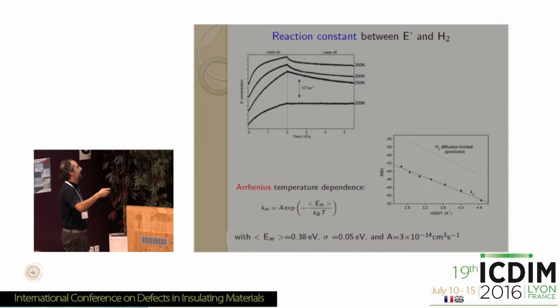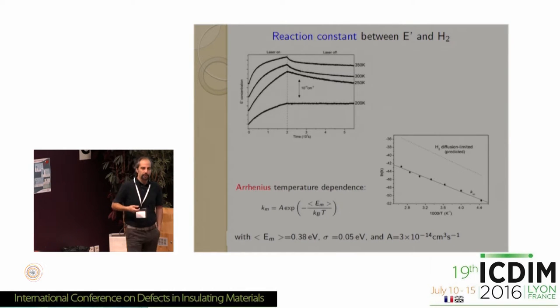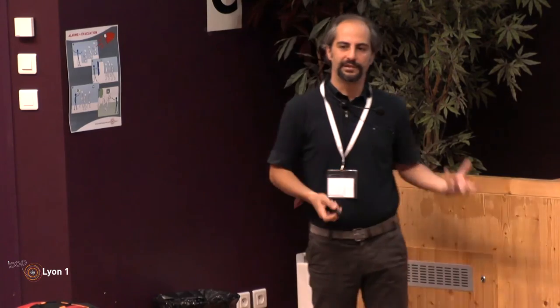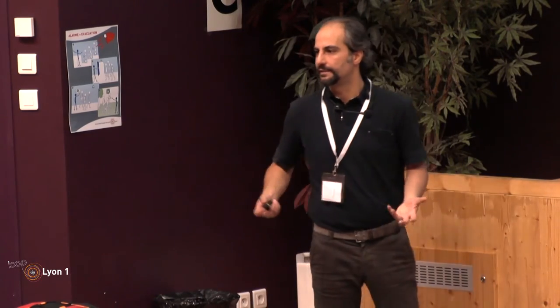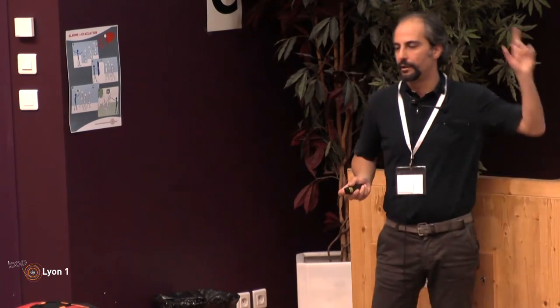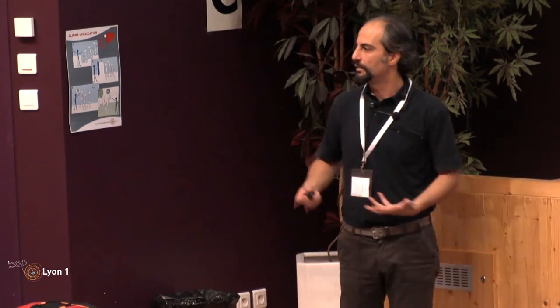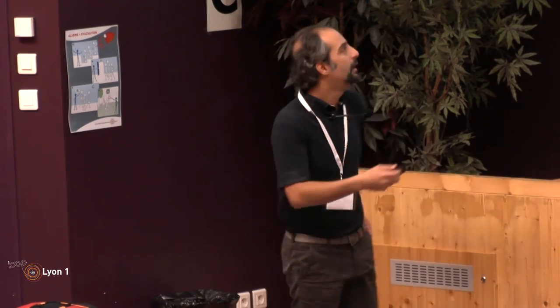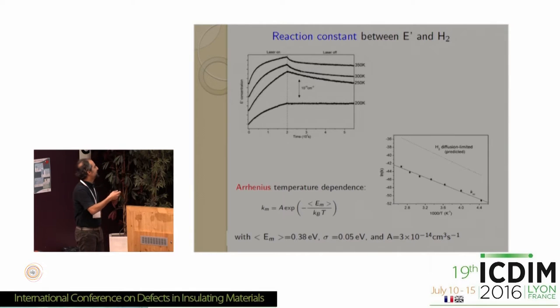And we found some quantitative parameters which describe the reaction constant between the defect and hydrogen, which are of some applicative interest, because of course hydrogen can be used to cancel the silicon dangling bonds, which means to recover transparency in the material, because these defects are responsible for strong UV absorption, and this characterizes their reaction with hydrogen in a quantitative way.